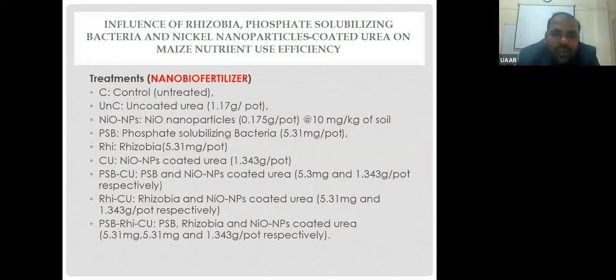Next is the influence of RHIZOBIA, phosphate solubilizing bacteria, and nickel nanoparticle coated urea on maize nutrient use efficiency. This is nano-biofertilizer, we call it, because we used microbes along with nano-fertilizer, so it is known as nano-biofertilizer. There were treatments, one was control and one was uncoated fertilizer, and nickel oxide nanoparticle, which was applied at the rate of 10 milligram per kilogram of soil, low dose, and then phosphate solubilizing bacteria at the rate of 1 kilogram per hectare. RHIZOBIA 5.3 milligram per pot, which was also 1 kilogram per hectare. And then CU, this is the coated urea, nickel oxide nanoparticle coated urea.